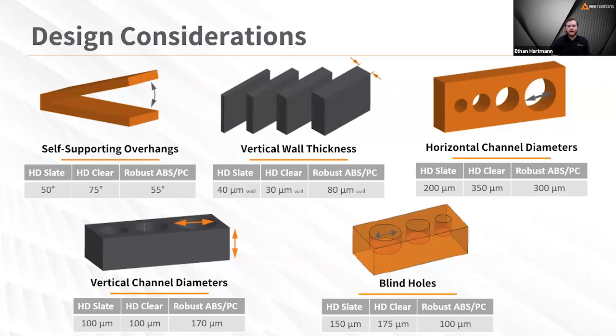So for the self-supporting overhangs, this is an angle measurement here, the angle between a flat surface and the printed surface. And the failure criteria was when there was individual layer delamination. As these layers print, the steeper your angle is, the larger the overhang of an individual layer is going to be. And at some point, that distance becomes so great that the individual layers won't adhere to the next ones. You get sort of a feathering effect along those bottom surfaces.